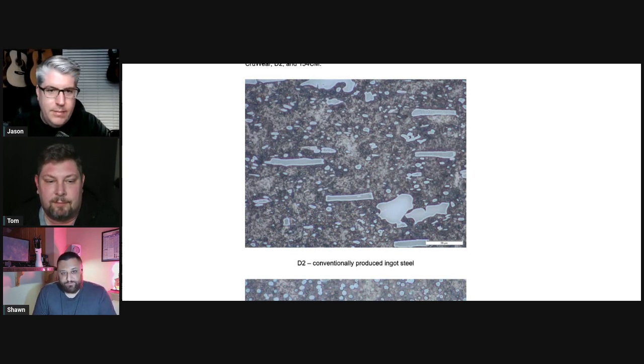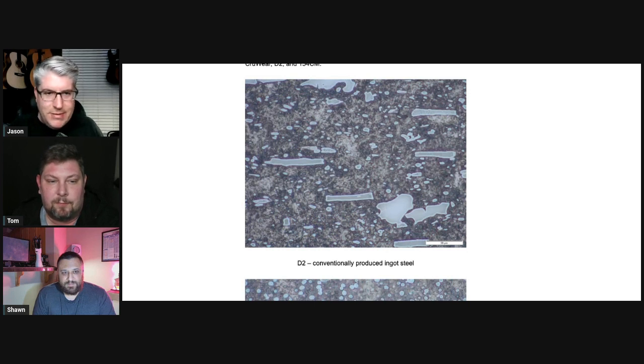That could be anywhere from 65, 66, 67 Rockwell, sometimes maybe 70 Rockwell, depending on how much carbon is in solution with that iron to make the tempered martensite. So the point I'm making is that if we made an iron knife blade, we would find that it would be really insufficient for being a knife because the iron itself is not hard enough. So we add additional elements to the iron to create the steel, and then the element blend will determine what the steel ultimately is, right?